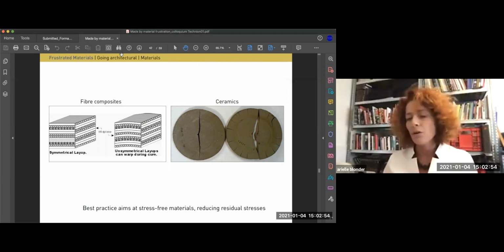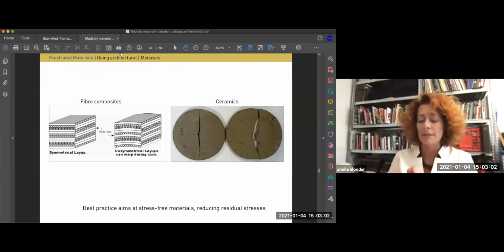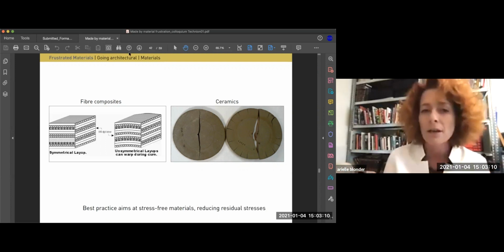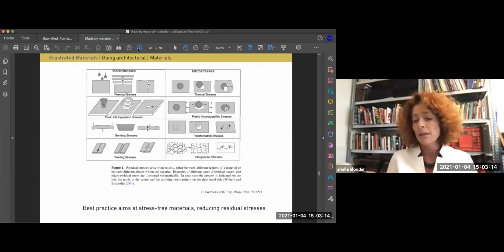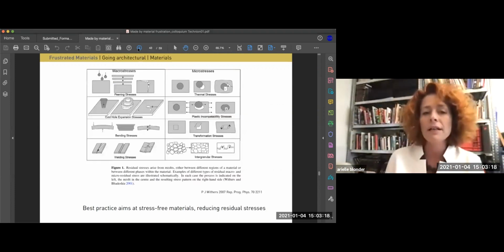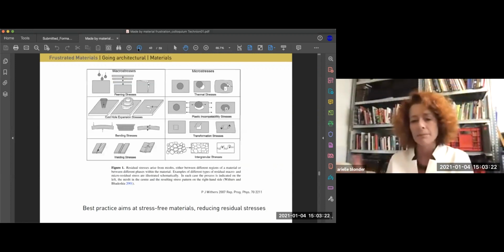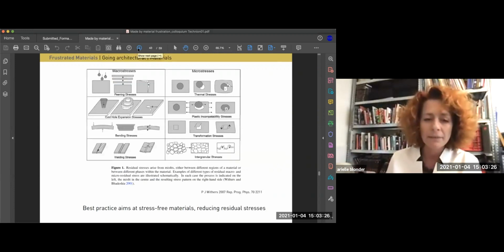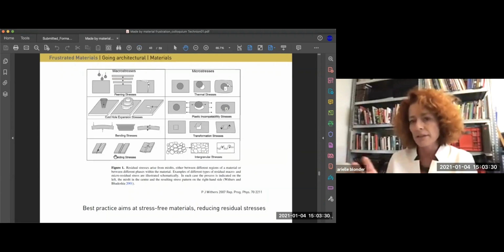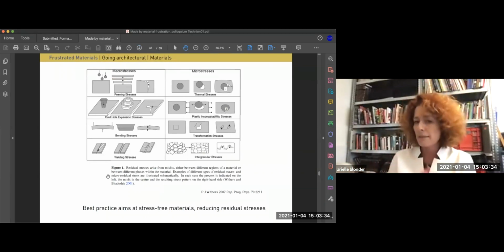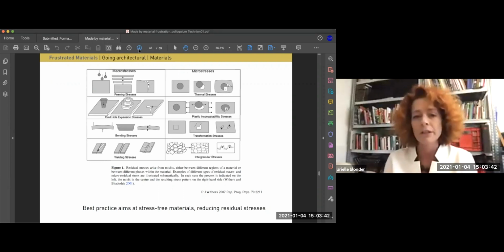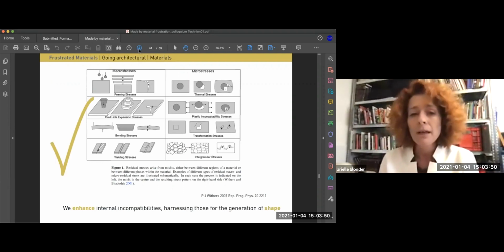Now, this goes against all that good students or best practice aims at doing. Best practice of fiber composites, ceramics, and any other material is to try to opt for stress-free materials, taking out all residual stresses. We don't want residual stresses to mess up in our system. Here we see another example. So here are all kinds of cases where residual stresses form in the material. It can be caused by many things, by heating, by bending, by transformation, whatever. And the idea is how to get this away, to have a balanced laminate for the composite and to have a proper ceramic arrangement with no differential shrinkage. What we say is just the opposite. We enhance internal incompatibility. We want this, we harness it to generate our shape.